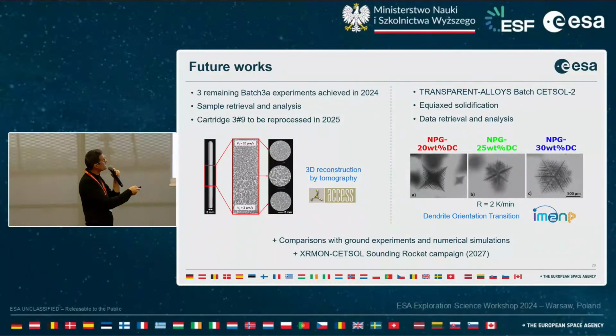And also a second batch of transparent alloys has been carried out in June, if I remember well. So once again, it was very successful and focused on equiaxed solidification. So we are looking forward to retrieving the data and start the analysis, where we can see here nice pictures of the equiaxed dendrites with, again, a change from 100 to 111 orientation. Of course, this will have to be compared with ground experiments and numerical simulations if we have the manpower, because this will be an issue in the future to find the manpower to analyze these data.